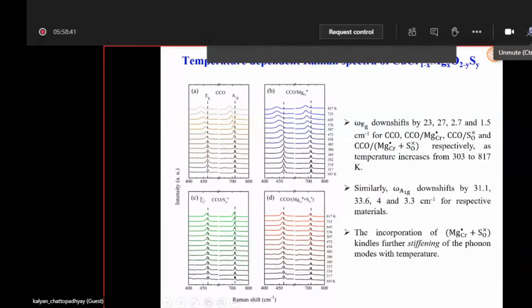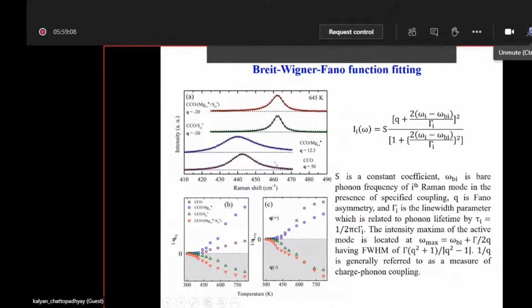Now, apart from this phonon softening and stiffening part, if you look at any one of these particular spectra and take a zoomed view, you can find what I was mentioning about Fano asymmetry or Fano resonance. You can find that the asymmetry in this peak is significantly affected. Taking one spectrum, maybe the 645 Kelvin spectrum, you just have a look. Here you see the 645 K sample at the peak: this is the pristine one, this is magnesium doped at the chromium site, this is sulfur doped at the oxygen site, and this is the simultaneous doping. If you fit this peak with the so-called Breit-Wigner-Fano function, then you can calculate this Q parameter, which is called the asymmetry parameter, Q, the Fano asymmetry. And you see here that for the pristine sample, Q comes out to be 50.